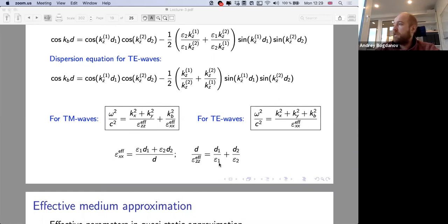But if you fabricate this artificial multilayer structure, like a metal-dielectric structure, 10 nanometers of metal, 10 nanometers of glass, and so on, this is a kind of metamaterial, because it's sub-wavelength, and it is a very strong, very anisotropic uniaxial crystal, where one permittivity is negative and one is positive. Do you know what I can call this material with different signs of ordinary and extraordinary permittivity?